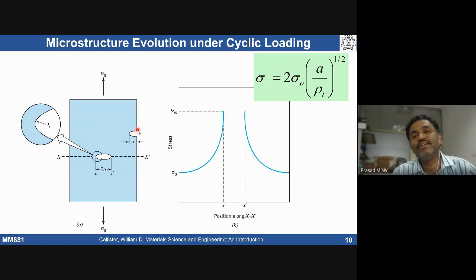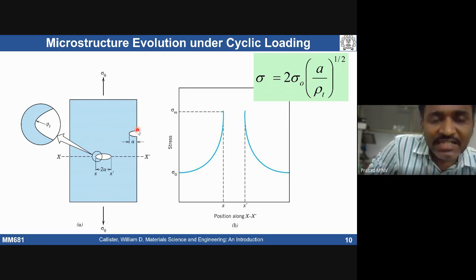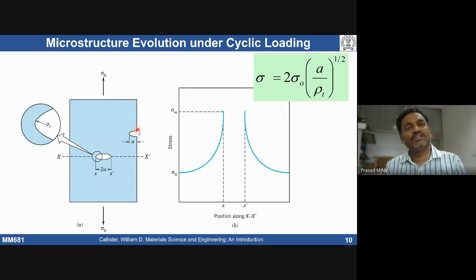So that's how materials fail under cyclic loading conditions, even if the applied stress is just below the yield stress. One cannot expect so much plastic deformation, but we may see some micro yielding that can lead to cyclic plastic slip activity, which can also generate cracks. Or if cracks are already present, like in polycrystalline materials where the grain boundary is already there, cracks can initiate very easily at the boundary, and that can lead to easy propagation.